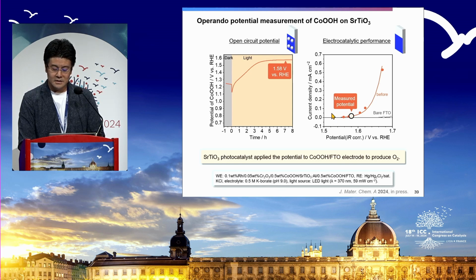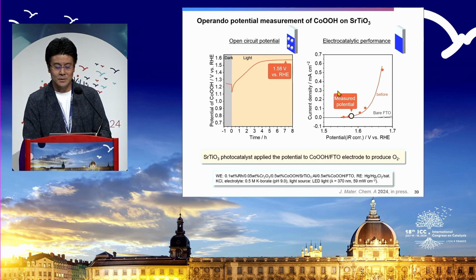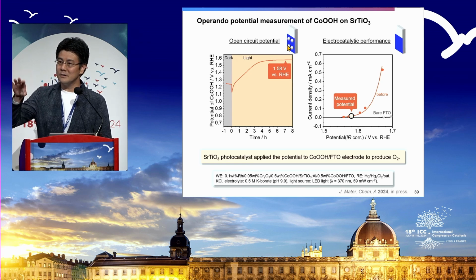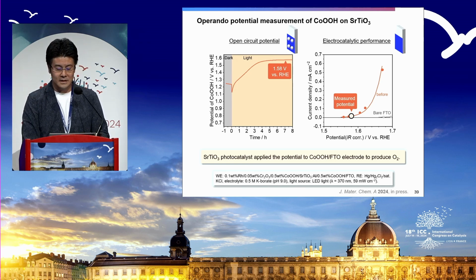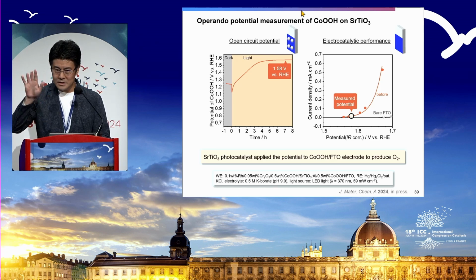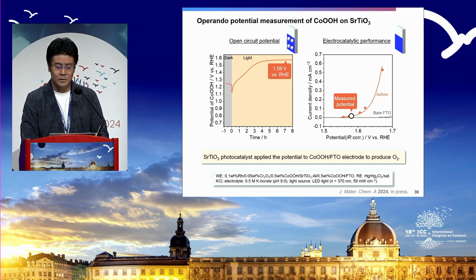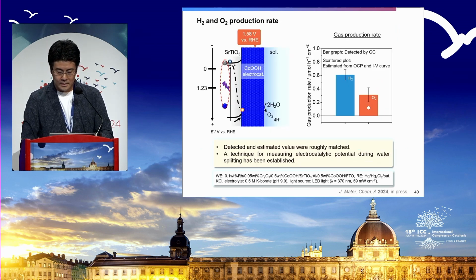Performance, so current density as a function of potential. And what we measured was 1.58, so it's actually here. There's very little oxygen evolution potential. This is because we wanted to minimize the accumulation of powders that don't have contact with this electrode. So we wanted to have a very small quantity of powders that are always in contact with this cobalt electrode. Anyway, what we see is 1.58 at the steady state.